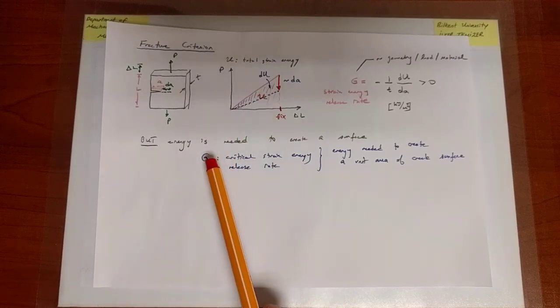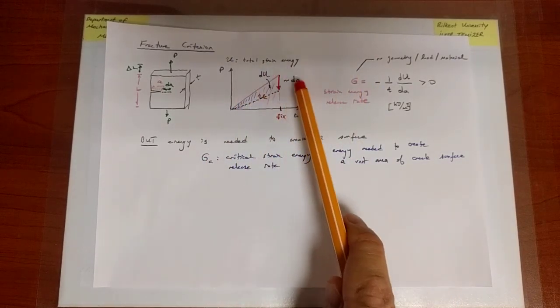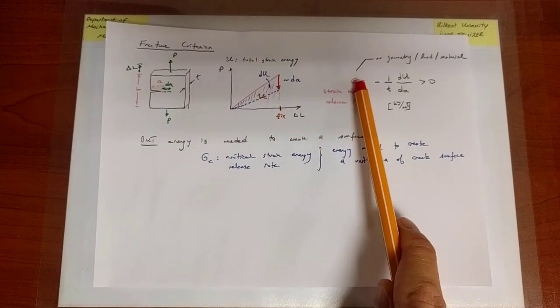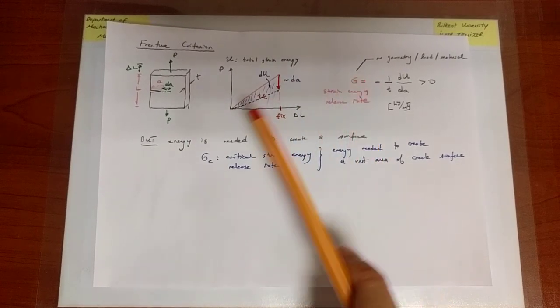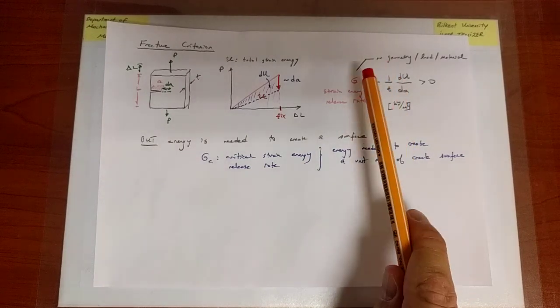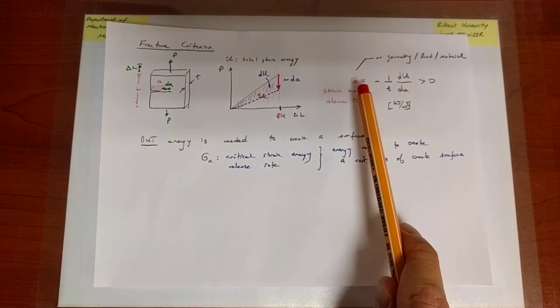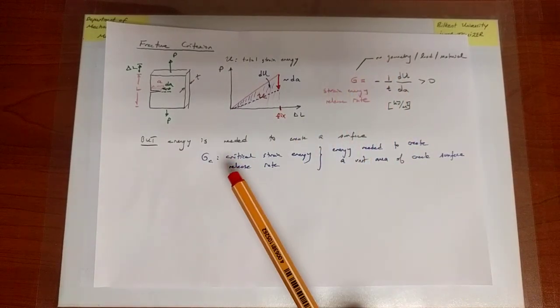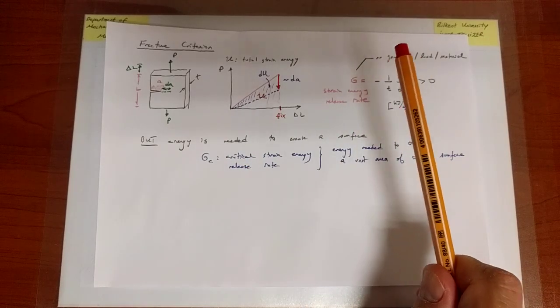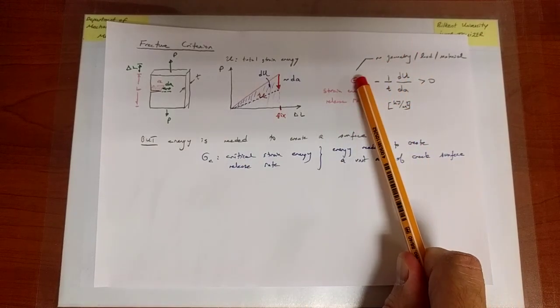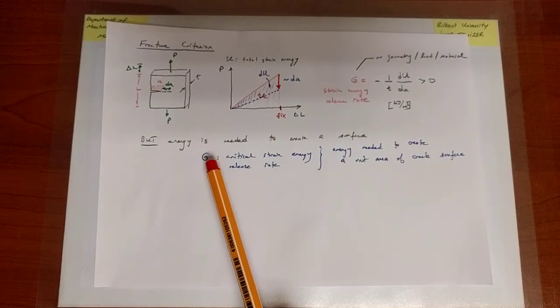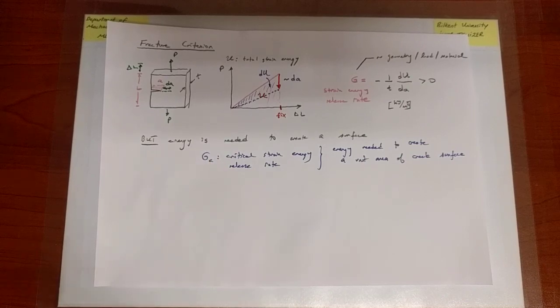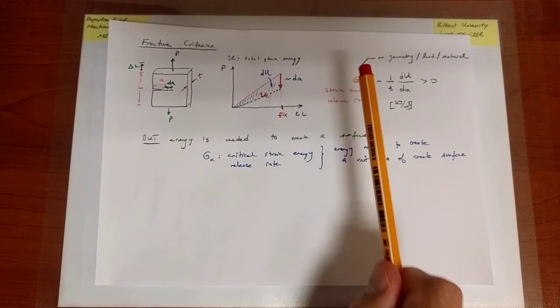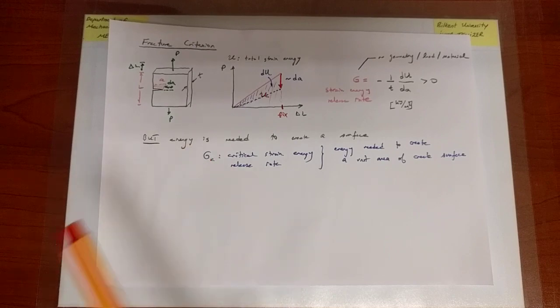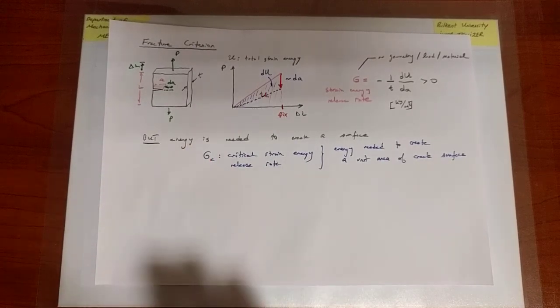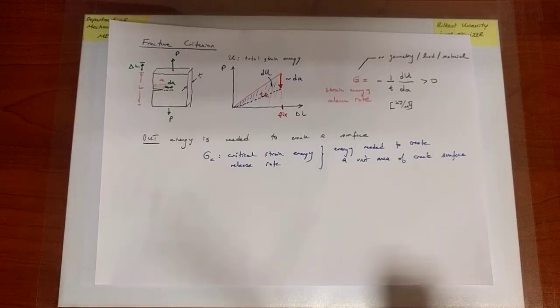On the other hand, at any stage of loading, what the system has available to provide into the crack propagation is G. That's the rate at which the system can release energy. So the system has, in rate form, G available. The surfaces need GC to propagate. So the question is, in terms of G and GC, can I predict whether the crack can grow or not?